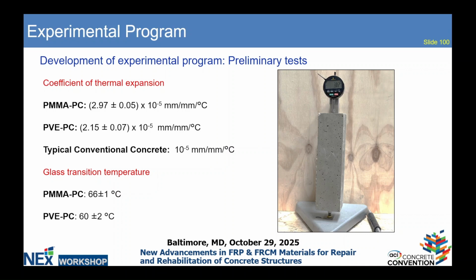And the glass transition temperature, we did a test for both of these. These results, the 66 degrees Celsius and 60 degrees Celsius, should be taken with a grain of salt, or a grain of sand, I guess.